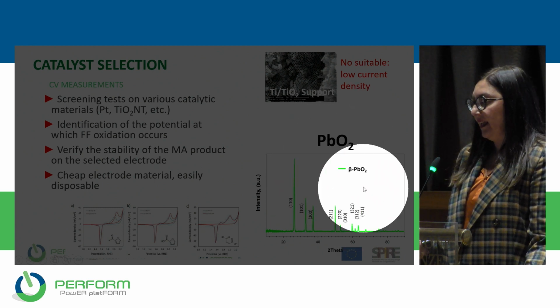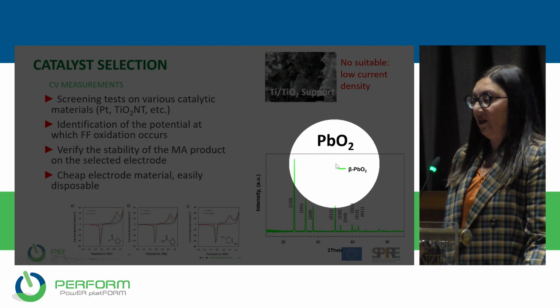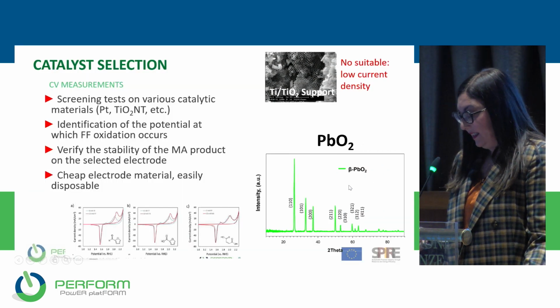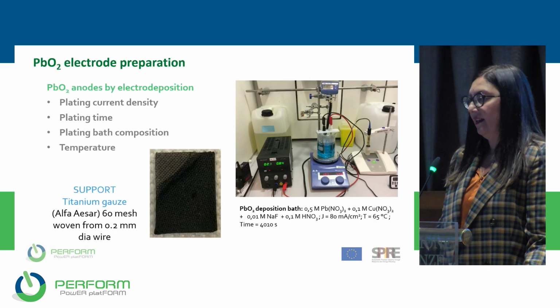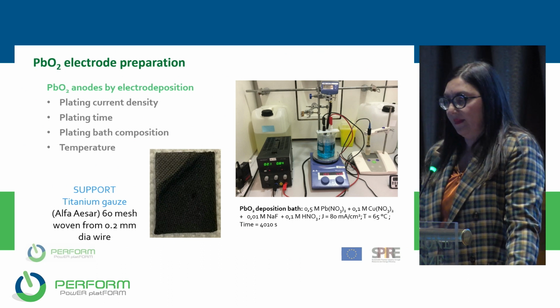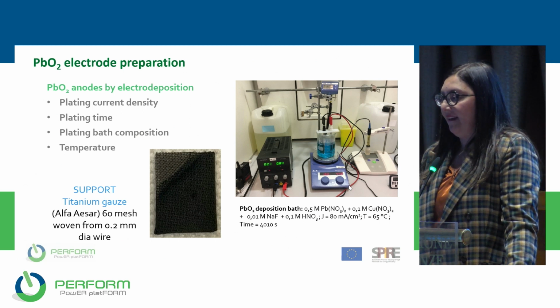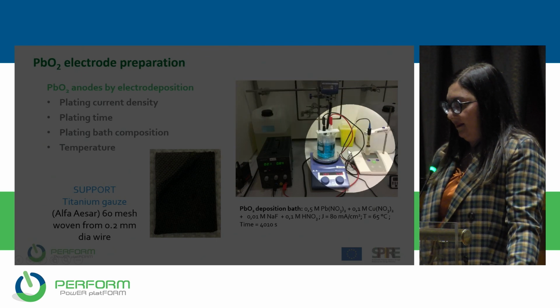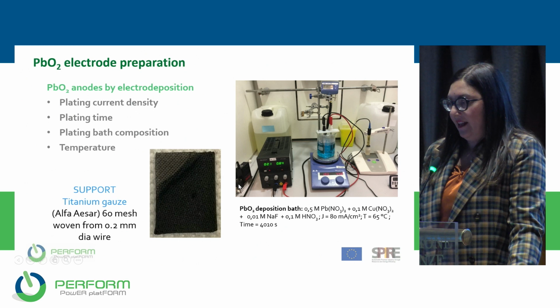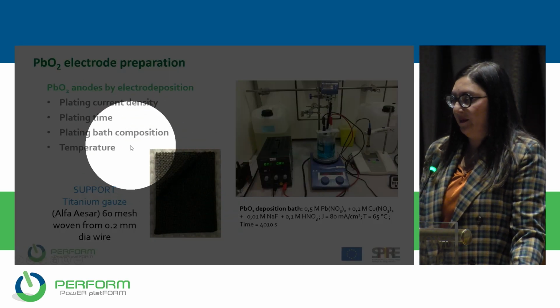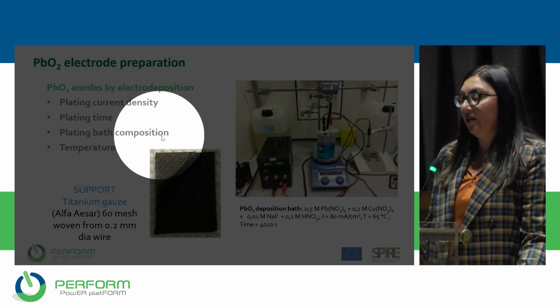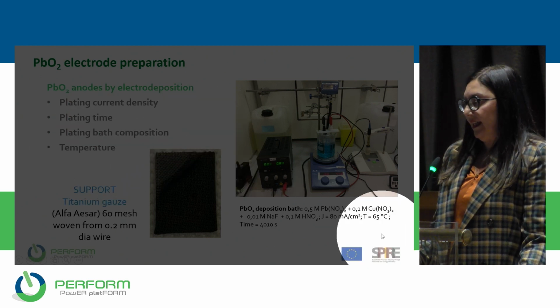And the lead dioxide was obtained in a particular phase that was more active than the other one, the beta phase. And the material was obtained by electrodeposition, and here is reported the electrochemical plating system and the conditions for the electrodeposition. Relevant conditions that have been investigated during the preparation were plating current density, plating time, the composition of the plating solution, and the temperature, because the beta phase requires a higher temperature to be obtained.